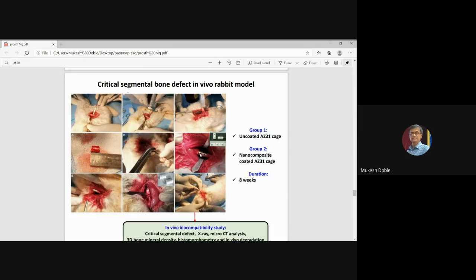You can see our cage here that's being placed inside. This is the cage, as you can see in all these pictures. The experiments were done for 8 weeks on rabbits. So we have two groups. The uncoated magnesium alloy was placed in rabbits for 8 weeks and then removed, and then the coated AZ31 magnesium alloy was placed, removed after 8 weeks, and then we looked at how the artificially created bone defect grew, what the bone density is, and what the key genes involved are, and how they all came out with respect to these two different materials.